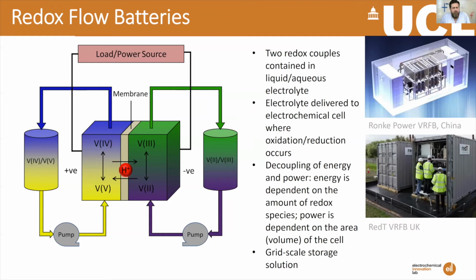Redox flow batteries are sort of a hybrid between a battery and a fuel cell, in that they have a central device that's akin to a fuel cell that does the conversion, the charging and discharging of the cell, and they have a sealed system containing the total charge of the battery. So in this case, this is a vanadium redox flow battery, and you have some tanks of vanadium 4 and 5 and vanadium 2 and 3 that have obviously a certain capacity.